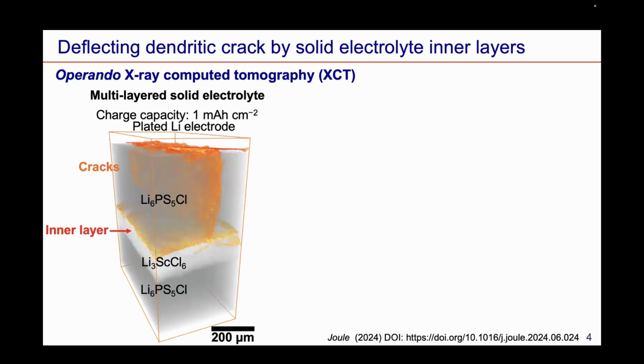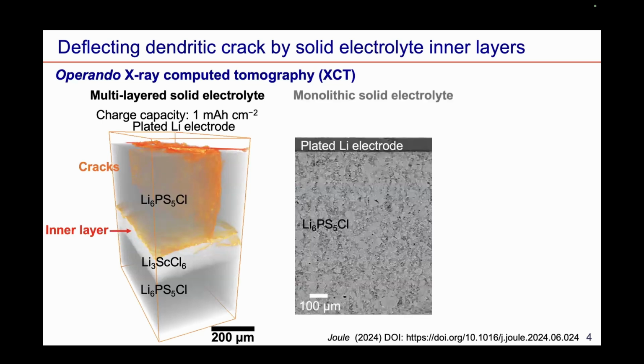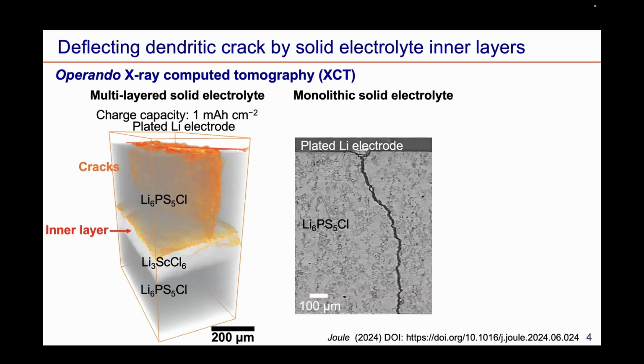This is very different from the behavior in a monolithic ceramic electrolyte. On the right is an XCT cross-section image of a battery based on a monolithic ceramic, lithium phosphorus sulfur chlorine, or LPSC. When we charge the battery, lithium is plated onto the top lithium metal anode, which induces crack initiation, followed by penetration of a transverse crack across the entire electrolyte without deflection. And this will lead to battery short circuit when this lithium dendrite connects the anode and the cathode.